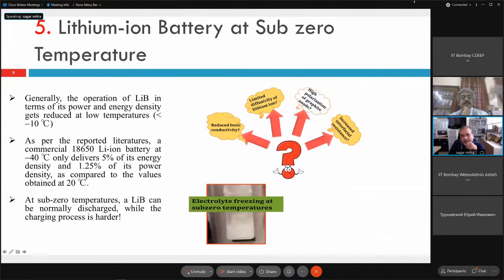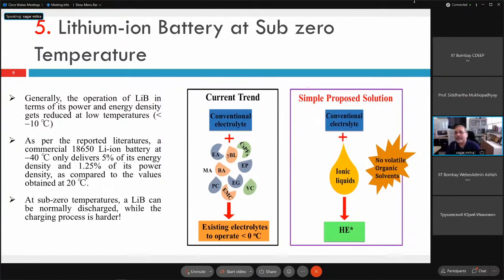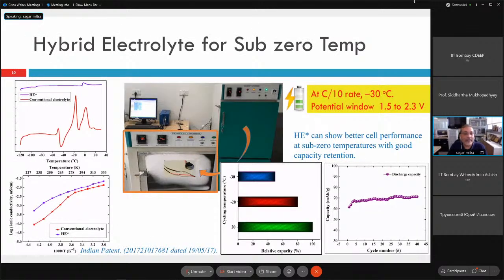Another problem of lithium batteries right now is that they cannot be used at lower temperatures, let's say 10 degrees or 0 degrees and below. That creates a lot of problems, because the liquid electrolyte composition you are using is not correct for low temperature operation. There are several things going on right now to replace the liquid component by other components. Here also we started working on different compositions, and one composition shows that we can cycle the battery at minus 30 degrees centigrade. This is another thing we started working on.